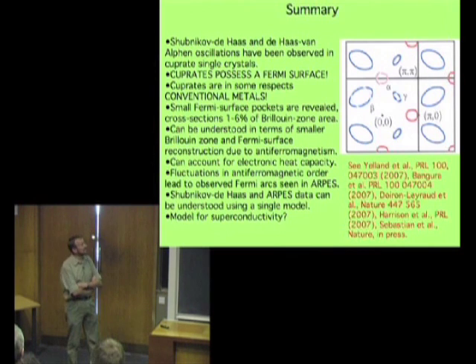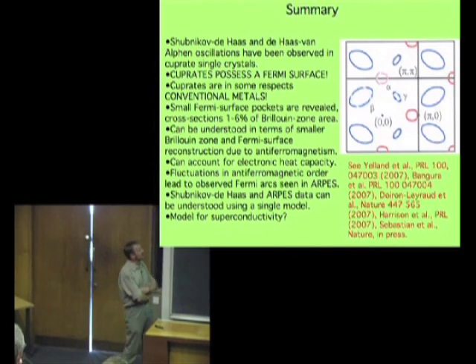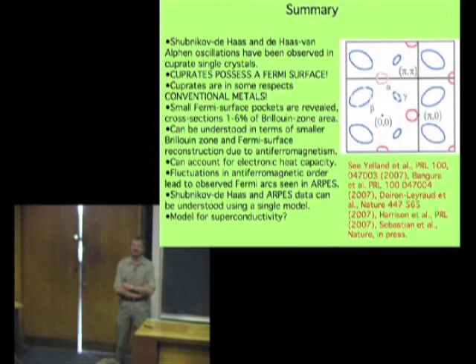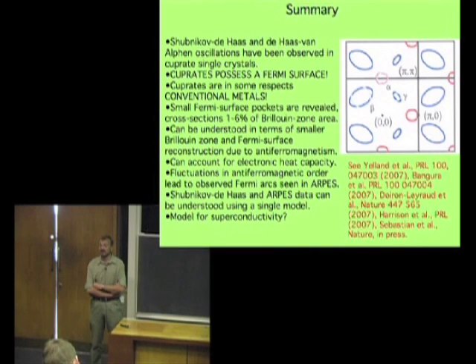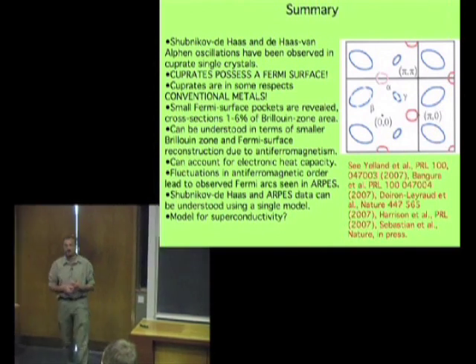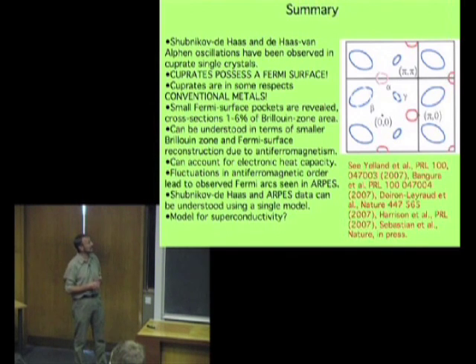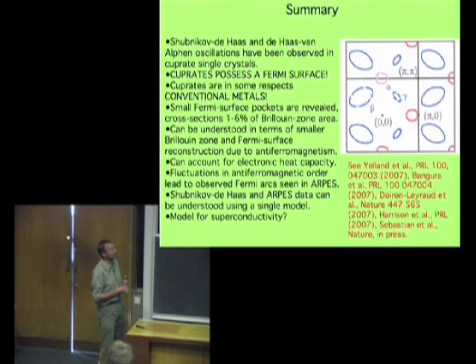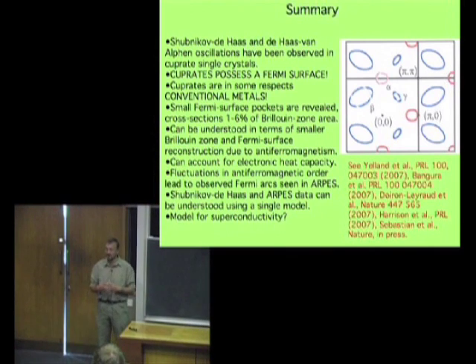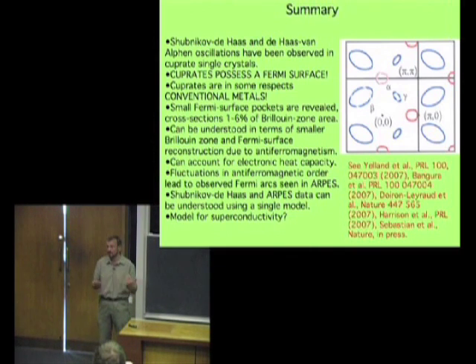Yes, and you would expect that they will be related in some way to the dynamic antiferromagnetism that you're seeing, because there's a strong magnetism-charge coupling. Because of the on-site Coulomb correlation energy, you'll get a strong coupling between the magnetism and the charge order, which is why antiferromagnetic fluctuations have an influence on what's going on with the electrons. So you would expect that anything that has a periodicity tied up with it in the magnetic system would also have a periodicity in charge, which you can pick up.